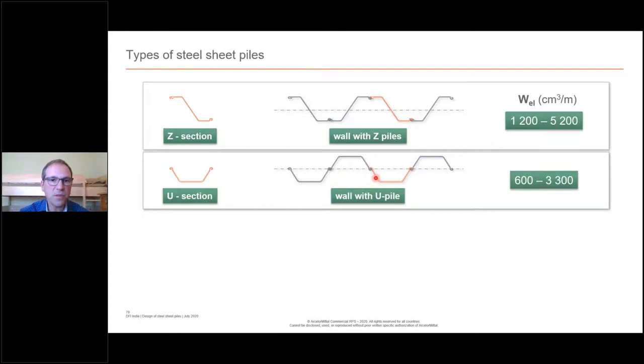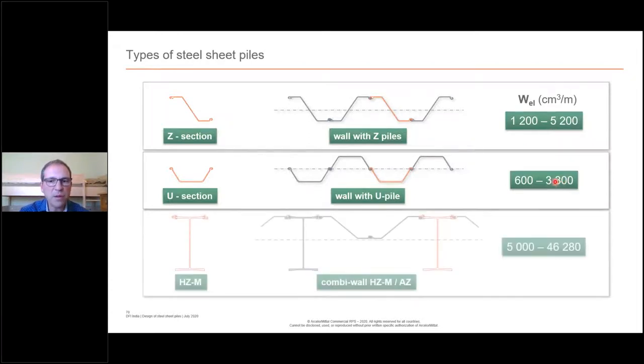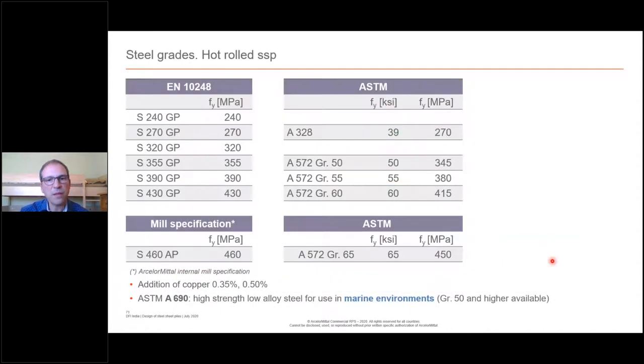the optimization. So for the sheet piles, for instance, you have a section modulus from 1200 up to 5000 if you take a Z pile, up to 3300 with the U pile, and for the combined wall systems you can go up to 46000, which is huge, but you have also a relatively heavy solution. So you have to find the optimum by combining the elastic section modulus or the plastic with the steel grade.